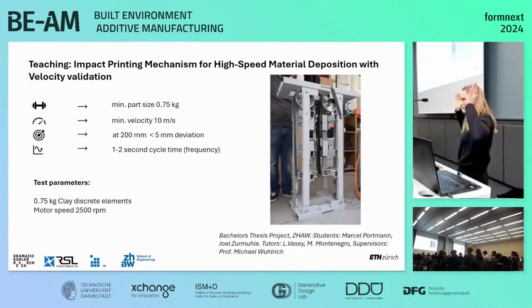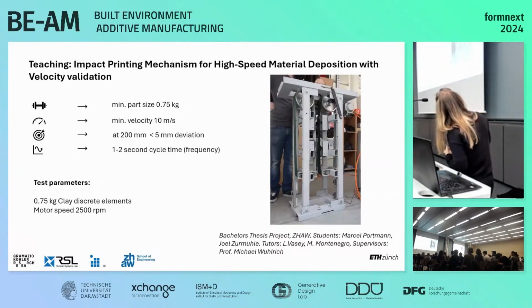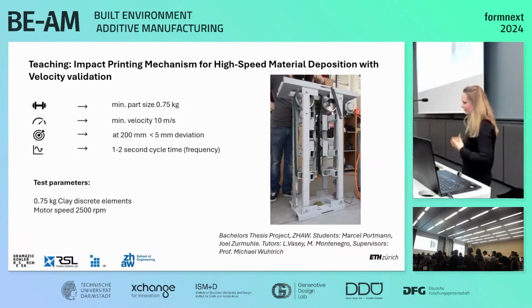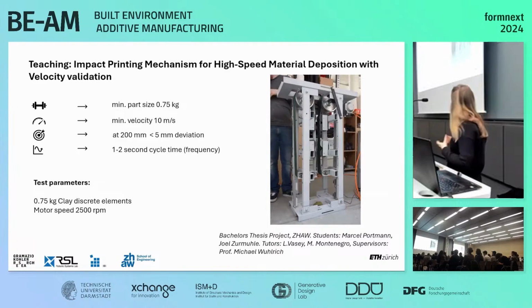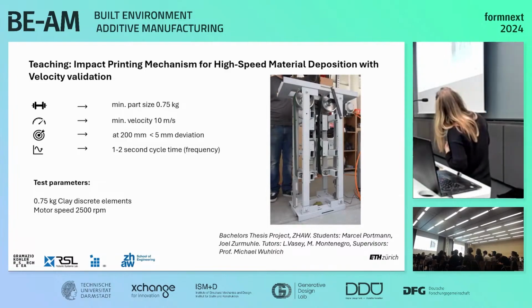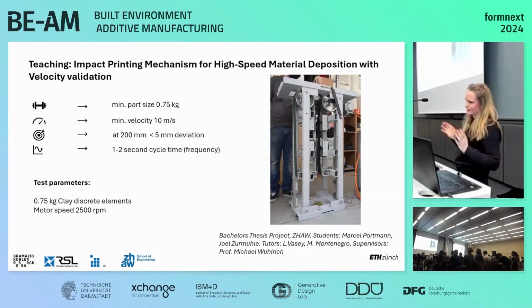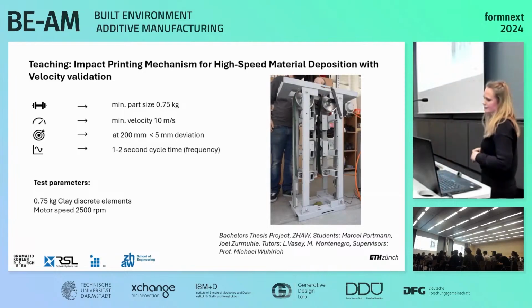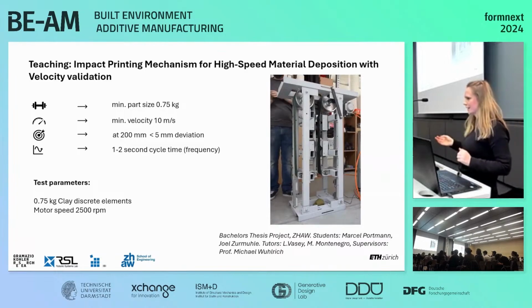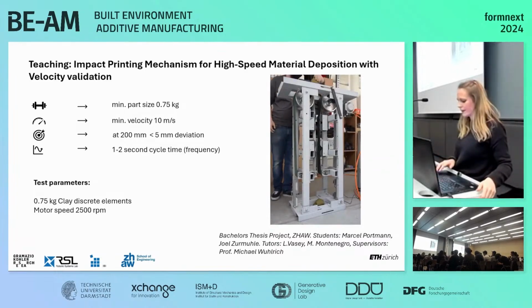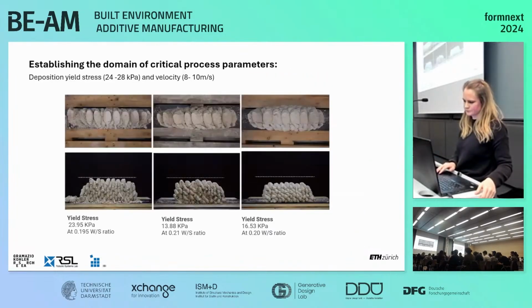Basically, we started with one belt-based system, which would have two belts that are rotating continuously. This means that you could enable a very fast cycle time. And we basically upscaled this concept. The target cycle time that I mentioned before is based on a build rate of 1 cubic meter to 2 cubic meters per hour. And so we were basically able to take this two-belt concept, accelerate parts, and achieve a very high controlled velocity, which we later improved in terms of accuracy.